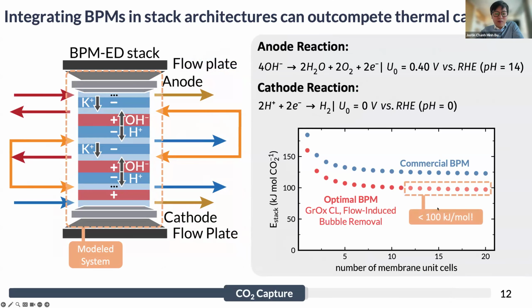And importantly, the thermal process is about 175 kilojoules per mole. With this optimized BPM, we think that we could get this process to under 100 kilojoules per mole per membrane. And so this could be a really interesting way to replace thermal calcination.